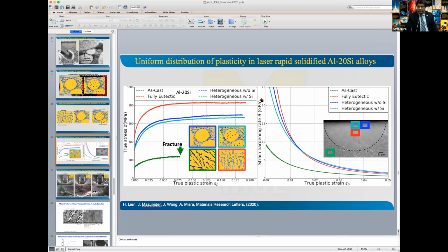Generally, if the material is high quality and you maintain the morphology that you have, then you should not expect to see an inverse Hall-Petch. Wherever people have seen inverse Hall-Petch, there was some other kind of instability, either contamination or an amorphous layer at boundaries or something else. They went down so fine that something else changed. And maybe Jagan has experience also.